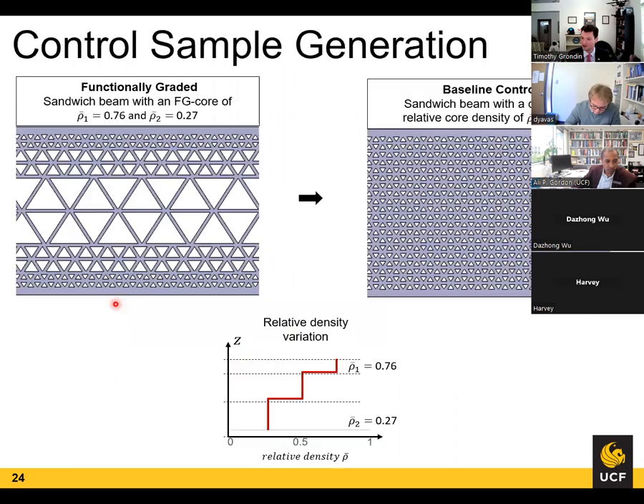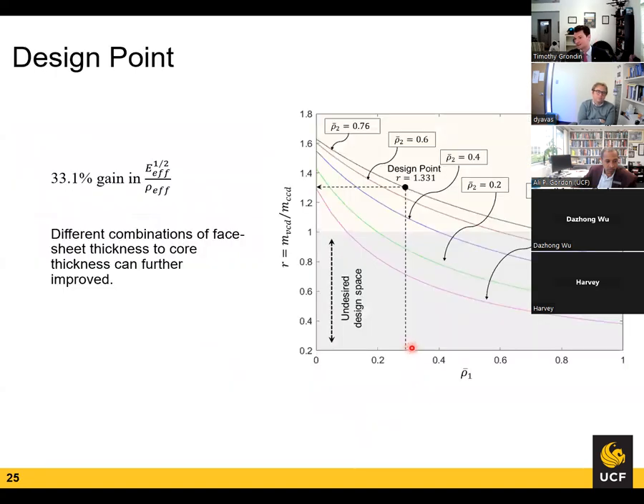And now we have numbers. We can actually put this back in. We just need to come up with a control. So because we half these each time, it was easy to come and just fill that whole thing in with 76% dense triangles. The variation can be seen in the center down here. We've already defined the density rows, and they can be seen with the 27%, and then coming all the way to the 75.9% on the outer one. All right. Now that we have that, we can plot our new design point. As we said before, we put a new line in here of 0.76 in MATLAB, and we took our 27% and we came out with a theoretical increase of 33.1% gain in flexural stiffness.